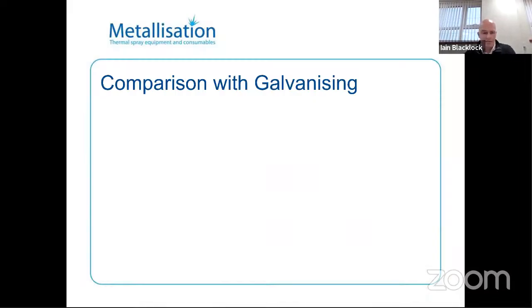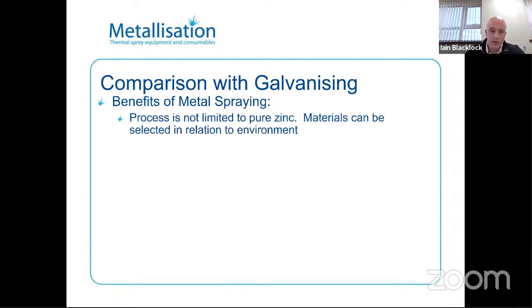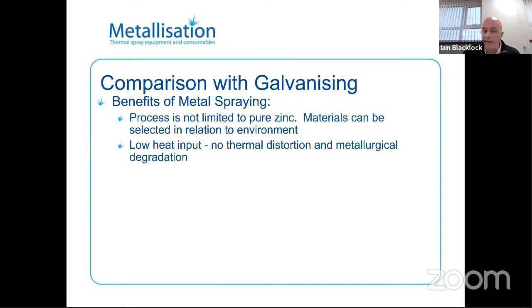So let's have a look at a comparison to galvanizing. Benefits of metal spraying. The process isn't limited to pure zinc, so you can choose a material subject to the application in relation to the environment. That means you can spray zinc al, which is very good in marine environments as an example. It's got very low heat input. So unlike with galvanizing where you can potentially get thermal distortion, you don't get that distortion with metal spray because it's a very controlled process with very low heat input into the substrate material.